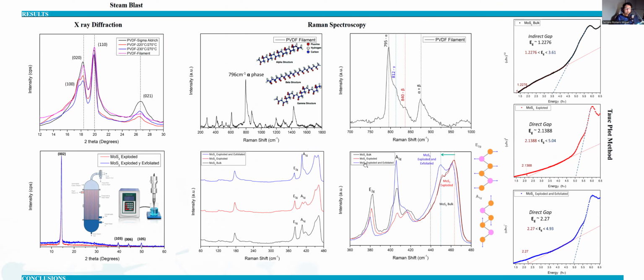Also for molybdenum disulfide, Raman spectra showed the expected E2G and A1G bands of the material, shifted in a way consistent with few-layer structures. So we can see the bulk material, the exploded molybdenum disulfide, and then the exploded and exfoliated molybdenum disulfide, and how the increase of the A1G mode and the prevalence of the E2G mode is associated with out-of-plane and in-plane vibrations.